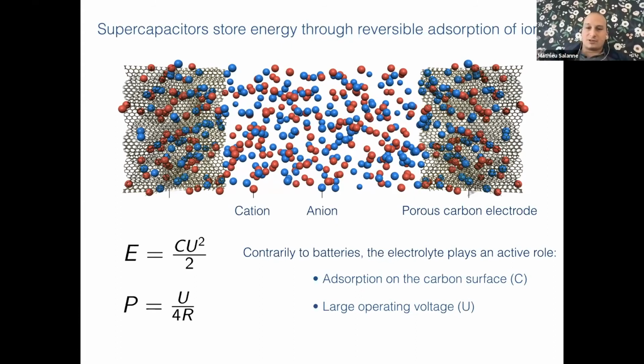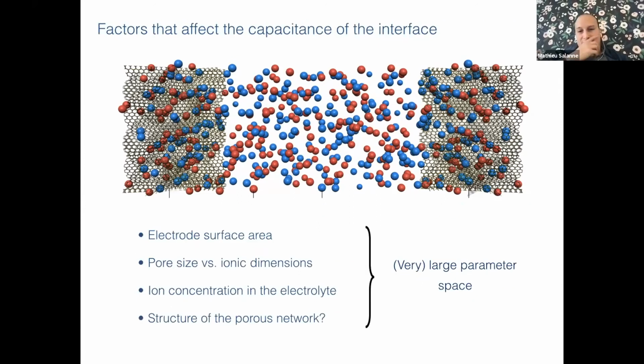So in fact, the most important thing on which people try to work is increasing the capacitance, which is the interfacial quantity. But in fact, this quantity depends on a lot of parameters. So you can change the electrode surface area, you can change the size of the ions, you can change also the nature of the solvent, you can change the concentration, you can change the porous network structure, because carbon, you can synthesize billions of carbons with different structures. So you are in a very large parameter space, and so there was no real systematic study until something like 10 years ago, I would say.